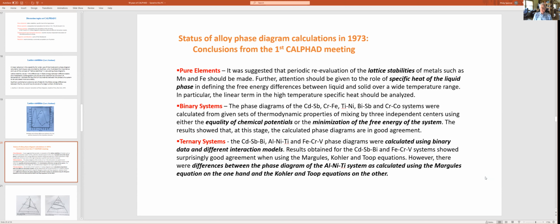With regard to binary systems, the phase diagrams of cadmium antimony, chromium iron, titanium nickel, bismuth antimony, and chromium cobalt were calculated from the given sets of thermodynamic properties provided by the three independent centers, and the calculations had been carried out using either equality of chemical potentials or minimization of the free energy of the system. The results showed at this stage that the calculated phase diagrams were in good agreement. With regard to the ternary systems, cadmium antimony bismuth, aluminium nickel titanium, and iron chromium vanadium, as I pointed out earlier, these were calculated using binary data and different interaction models to obtain ternary properties.